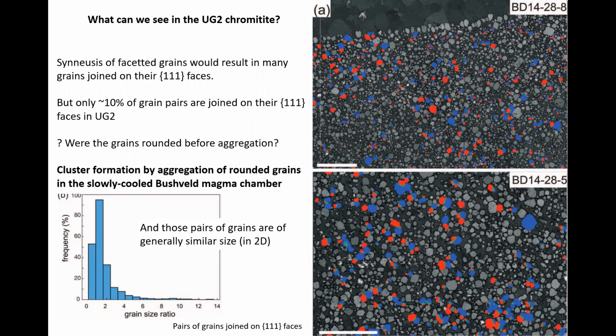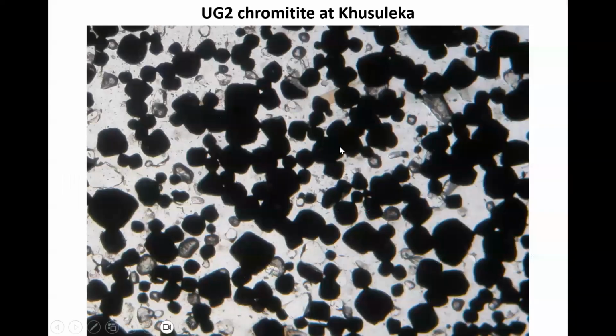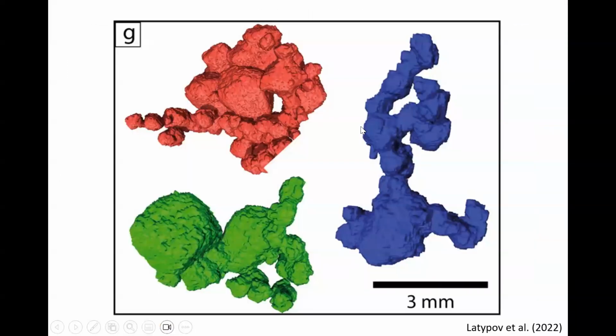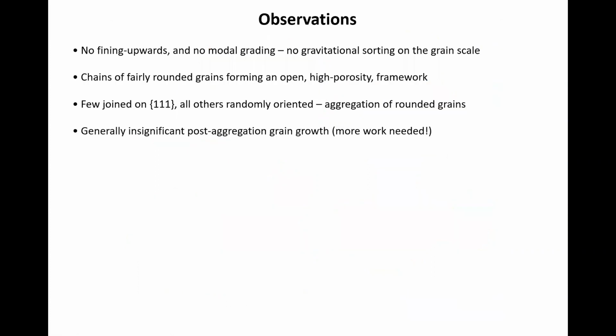We don't see overall fining upwards, and we don't see any sort of clear progression of grain size along these chains. Now, what we do need, and this is where we're losing information, is that all I can see is 2 dimensions. What we need is 3 dimensions. And this is where Steve Barnes and his amazing tomography needs to come into play. We need to see if there's any systematic change in shape or size along these chains in order to argue for the in situ aggregation.